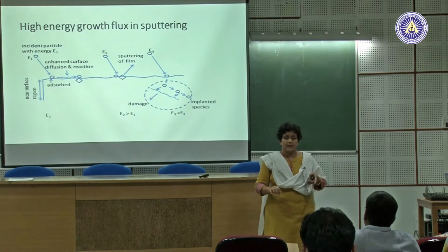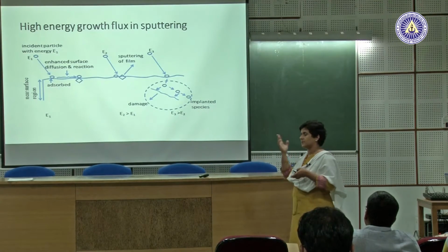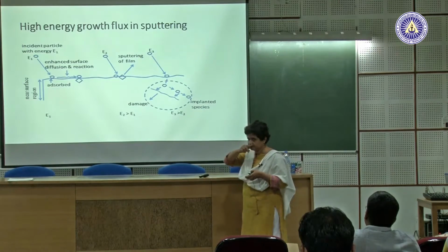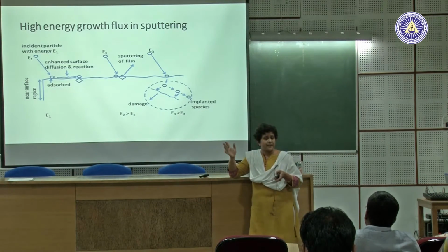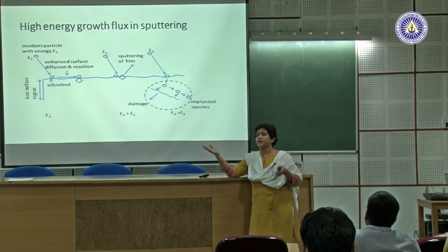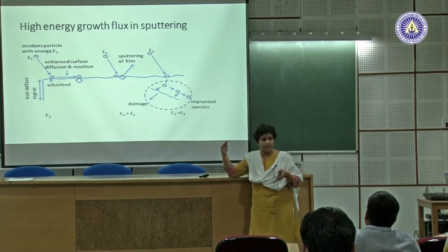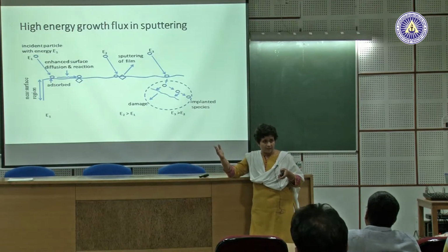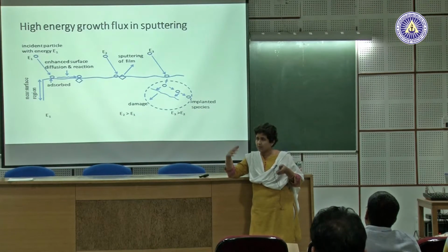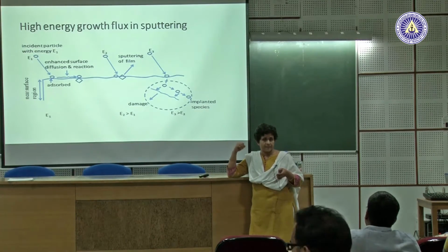that you want. And that is why, for example, let us say I am sputtering silicon. If the substrate temperature is low, the silicon that I sputtered will form an amorphous film on the substrate. I keep heating the substrate temperature. I have a heater over there. I can keep heating the temperature. From amorphous, I can make a polycrystalline. I still further heat it and provide some other activation energies. I can make single crystalline silicon using sputtering.